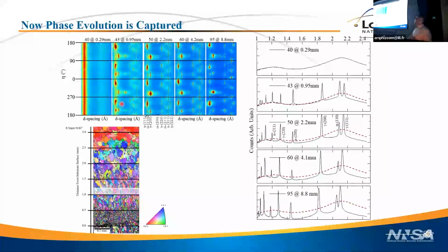You can watch the phase evolve. So these are the same positions here, just integrated now over eta. This is the liquid, and I've transferred the liquid diffraction pattern here in the dashed red line. And you can see as it solidifies, these are the ferrite and austenite peaks, the two phases of the steel. But you can see there's still liquid scattering there. So at this point, we're seeing liquid and both solid phases. Now remember, that I haven't really focused on this, but we're integrating through the thickness of this. And this is another issue, is that we're certainly going through a temperature gradient. So if I look at this, you might say, oh, wow, I have liquid and two solid phases all in equilibrium. That may not be true.